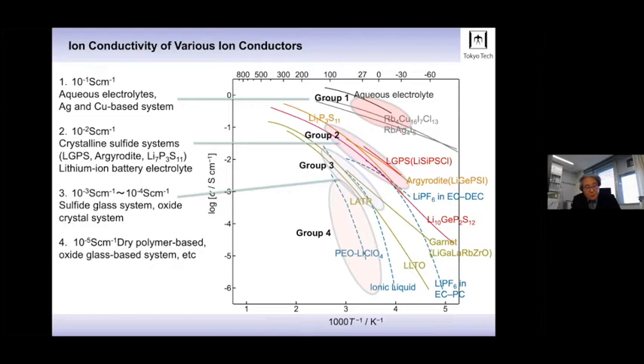The third group is the oxide-based lithium garnet, with much lower conductivities. Other materials, like polymers, have lower values. The higher the ion conductivity of the electrolyte, the more power the battery has. It is clear that the lead acid battery, with this conductivity region, can take higher current more easily than a lithium-ion battery with the second electrolyte group. This is the issue for the lithium-ion battery: the low ion conductivity of the electrolyte.